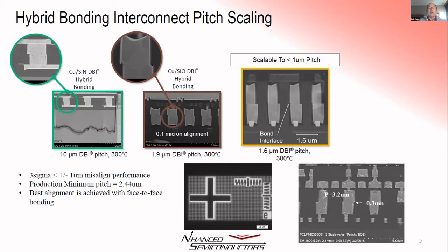You get a van der Waals bond, and then we come back later and we do a higher temperature anneal to drive out dangling hydrogen at the bond interface, and it promotes copper growth across the boundaries. And you end up with a structure that is as if it was sequentially manufactured. So it's virtually boundary free.